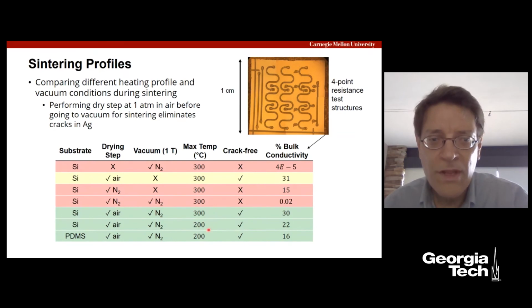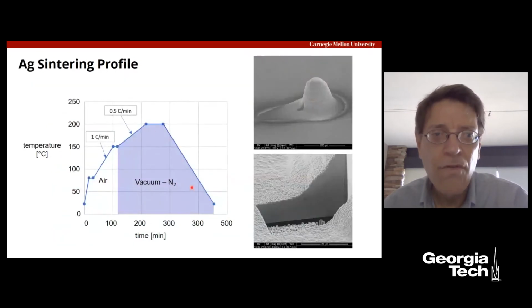While we could go at 300, we found that at 200 we're going to get better PDMS behavior. So this is our recipe now, and we have a certain profile going through this of, again, a drying step at 150 C and then going up to 200 in the vacuum. So limiting the air exposure at 150 for the PDMS is critical.